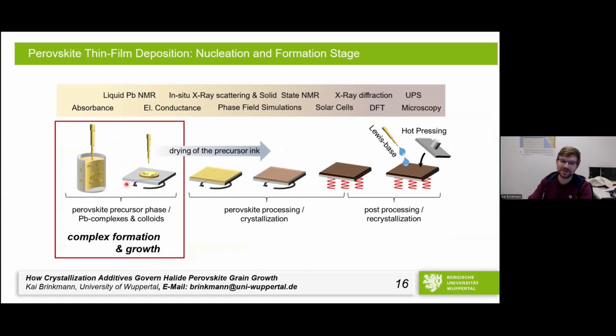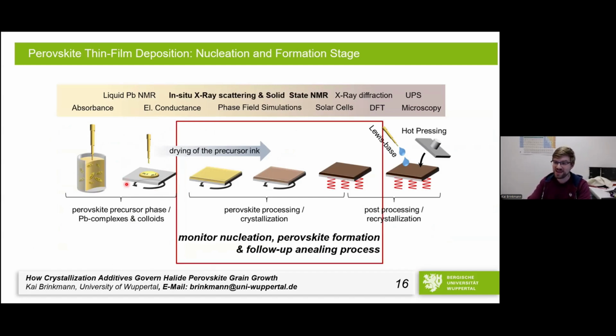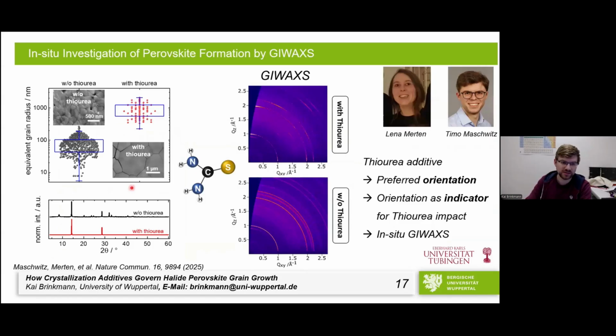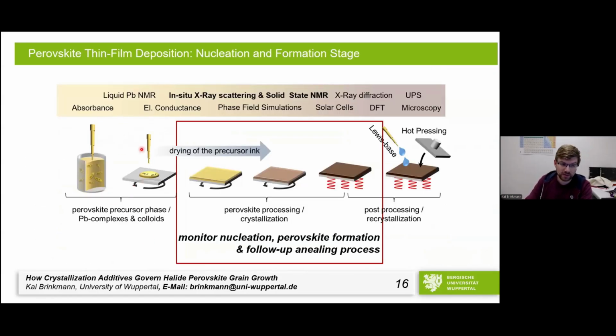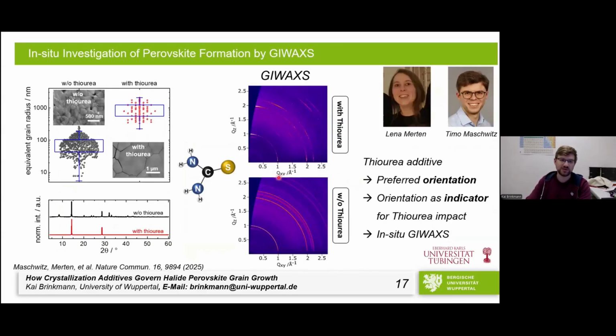So now basically Lena Merten comes in, because we got the idea, maybe we were wrong. Maybe we are looking at the wrong part of the process. And this is why we went away from the lead precursors and went back into the perovskite formation process by doing grazing incidence wide-angle X-ray scattering, which Lena Merten is able to do at DESY, and she's able to do in situ studies. So with this one, we were actually able to probe the perovskite while it formed. And what we did is basically the same stuff that we did before.